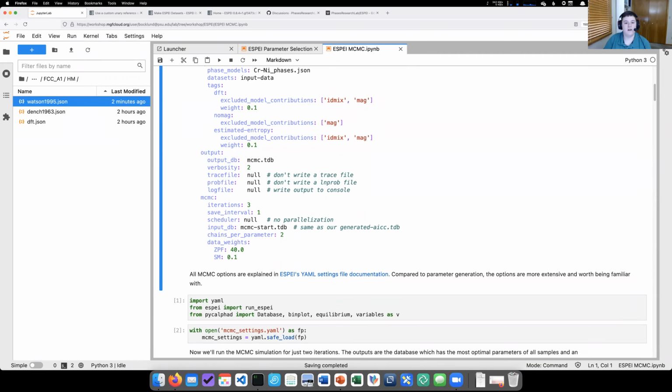Yeah, so for this one, what this is excluding is the CALPHAD type TC and BMAG parameters. And so the interpretation of this is that if you were to do a finite temperature DFT calculation, even if you have spin polarization, you can't capture the magnetic ordering energy, right?